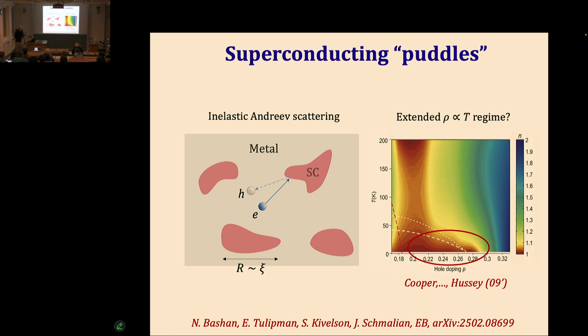If you have these puddles above the bulk TC, it's a bit strange because they're still superconducting. Yes. And for sure there will be some Josephson coupling, or maybe not for sure, but there may be some Josephson coupling, which would probably show up in the IV characteristics. So going to very, very low currents you would start to see a better and better conductor. Is that so? Right, so in this analysis there's one thing we ignored. We thought about scattering of the normal electrons off these puddles, but then we can also have a Josephson coupling between puddles, and eventually that's what would cause the system to go superconducting.